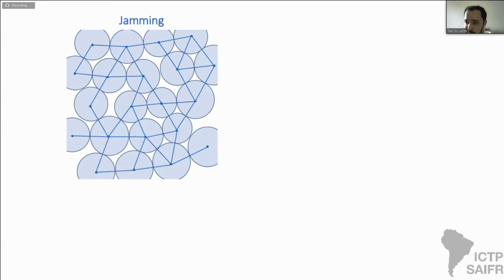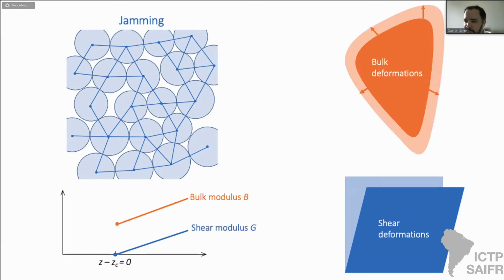In the traditional way of describing this ubiquitous transition called jamming, one compresses a bunch of frictionless spheres until they form a disordered contact network that resists compression. Now you can describe this rigidity transition by looking at the behavior of the elastic moduli associated with bulk and shear deformations, as the average number of contacts increases to above what we call the isostatic point of mechanical stability, ZC.